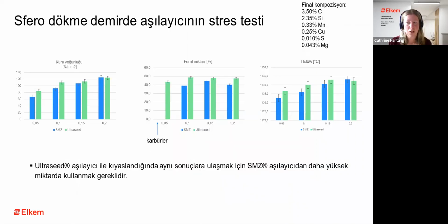So in this last example, we are looking at the results from a stress test of Ultraseed versus SMZ in ductile iron. By stress testing, what is meant here is that we're trying the inoculants at different inoculation additions. So we try to go really low in ductile iron. I think you would agree with me that 0.05 weight percent addition in ladle is a very low addition for ductile iron. And then we have different addition rates. And I should say also at the same time that we are adjusting, so the final silicon is the same. So although we have different addition rates of the inoculant, the final silicon is the same.